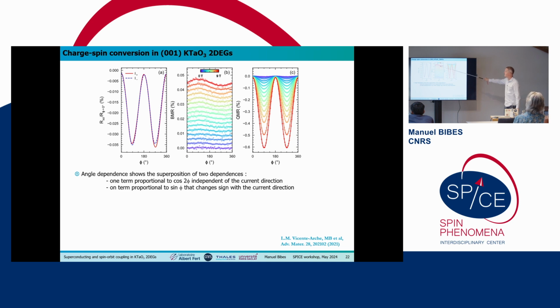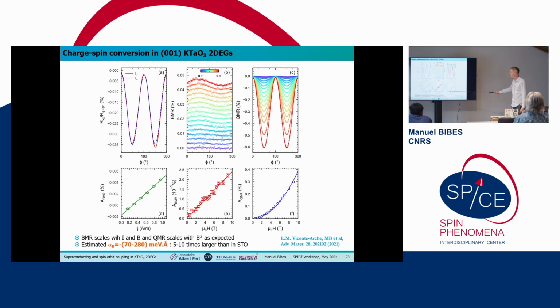And this is the bilinear magnetoresistance, and this is the other one, which we call the quadratic MR, QMR, because it scales with the square of the magnetic field. And this one really scales linearly with the current and the magnetic field. So it's bilinear indeed. And from the amplitude of these 2 contributions, we are able to extract the value of the Rashba coefficient. Unfortunately, it also depends on the g factor, which is not very well known in this system. So we just get some kind of range, making an educated guess on the values of g.